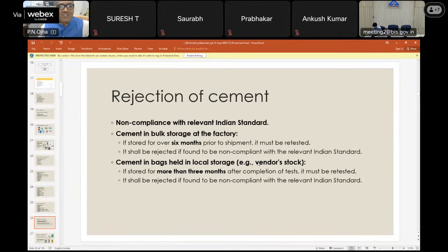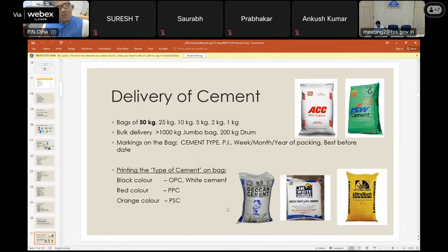And rejection of cement, as I said, cement is supplied in bulk storage and bulk bags, but when there is non-compliance with relevant standards, then it can be rejected. Okay, and if it is more than 3 months old, then it should be tested again, and if it is not meeting the criteria, it must be rejected. So these are the rejection criteria mentioned in the specification standard. Okay, and delivery of cement, generally 50 kg bag, but sometimes 25 kg, 10 kg, 5 kg, 2 kg, 1 kg are also standard. But it happens in the case of white cement, but generally not in the case of gray cement.